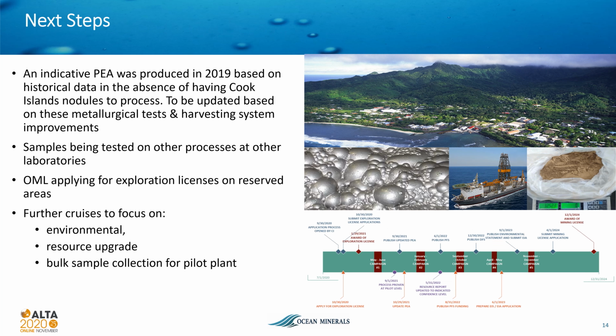Before Ocean Minerals had recovered and processed nodules from the Cook Islands, an indicative preliminary economic assessment was produced by AMC Mining Consultants in 2019 based on historical data. AMC used the resource data produced by RSC. AMC also reviewed historical mining and processing information. This data did not result from work done on Cook Island nodules, but on other nodule deposits, particularly those in the Pacific's Clarion-Clipperton zone. Following the recovery of the nodules in the research cruise, better data has now been achieved.